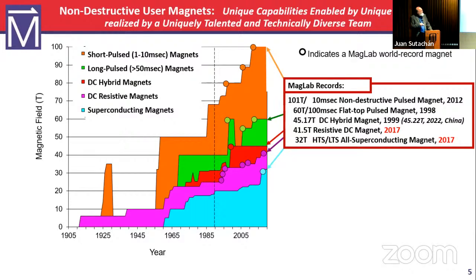The resistive magnets are the expensive ones to run. They're electromagnets, and we power those with our power system. The hybrid magnet uses both resistive and superconducting magnets to get to 45.17 Tesla, the highest DC field in the world that we've reached in 1999. 2 weeks ago in China, they announced 45.22 Tesla, which is 0.1% higher field. And we believe they'll be operating their magnet, as do we, at 45 Tesla.